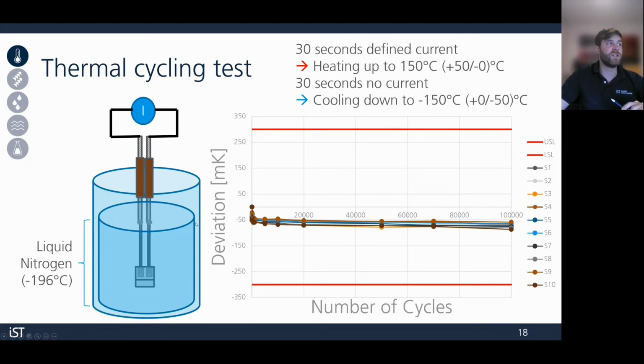We have here the deviation in millikelvin, and this is from the two-bath test, the deviation in millikelvin of the resistance at 0. So we're extrapolating down to 0, and we see very little drift. The USL and LSL lines here are the allowable limits according to the detail spec.